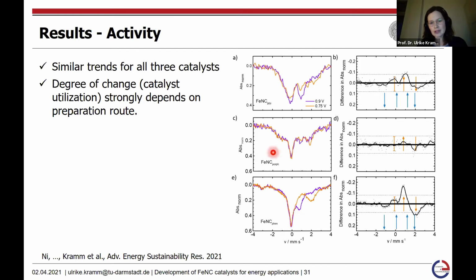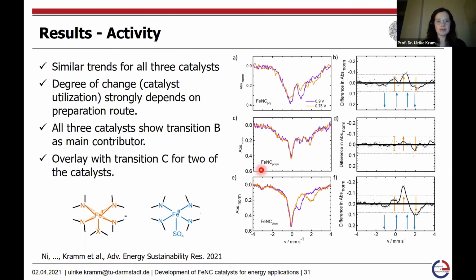First of all, you can see that the changes are not equally pronounced for the different catalyst materials. That means we only have a partial transformation of the catalyst to the deoxygenated state. Here are the original spectra, and here we have the difference spectrum. What you can see is that for two of the catalyst materials, we can identify two of these transitions, but for one of them, there are so far only small indications of one of these transitions. We were not able to see transition A, but only transitions B and C, which are associated with these two deoxygenated states.